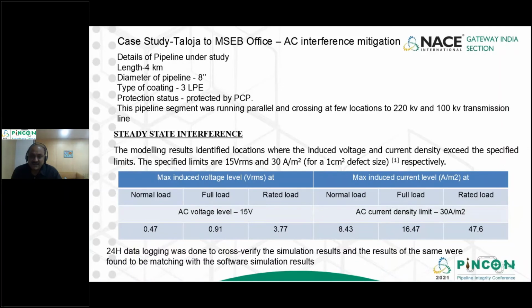The specified limits are 15 volts and 30 amps per meter square. So at normal load, full load, rated load, if I see the maximum induced voltage levels, the AC voltage limit is 15 volts, and the current density as per the standard is 30 amps per meter square. What we were getting around the normal full load and rated load is around 3.7, so voltage was not a big issue. For the induced current at normal full load and rated load we were getting 47.6. This was at a particular location.